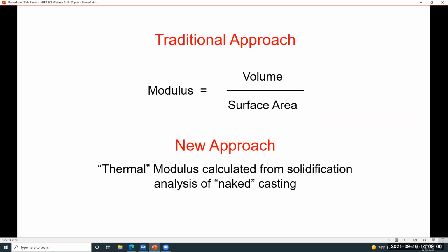The traditional approach to riser design is commonly called the modulus approach or the modulus method. The modulus is simply the volume of the casting divided by the surface area. Now, that could be of the full casting, or it could be for different parts of the casting. And this was really a concept that was developed almost 100 years ago. And the idea behind it was that the volume represents the heat or the energy that needs to be removed in order to get solidification to occur. And the surface area is where that heat goes. So if you have a given size casting, you have a given amount of volume. If you have more surface for that heat to flow out, then that heat is going to be removed more rapidly and will have a quicker solidification time. So the modulus becomes a rough equivalent of solidification time.